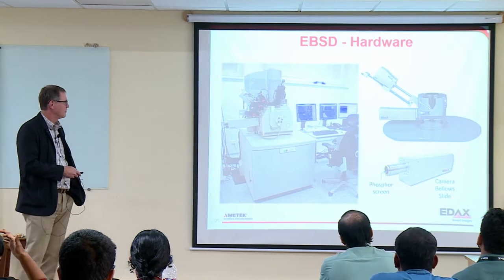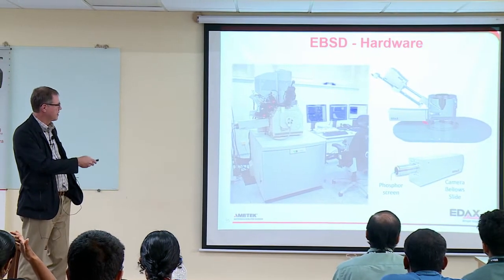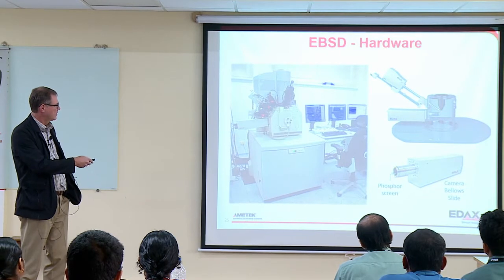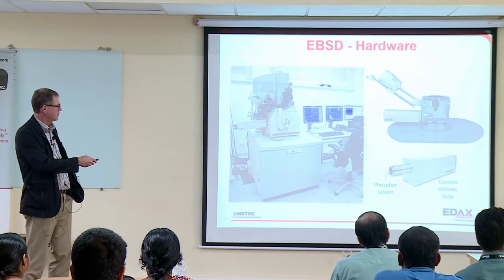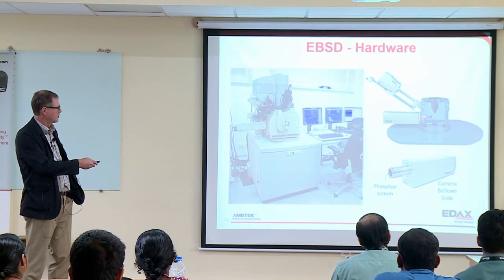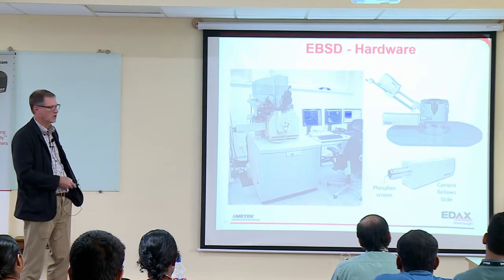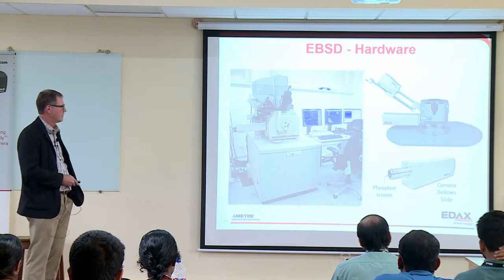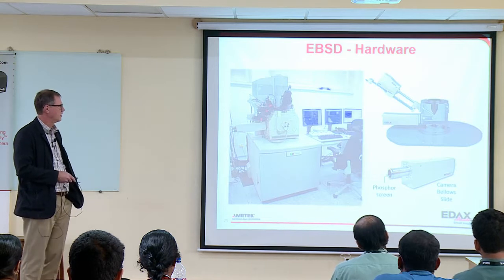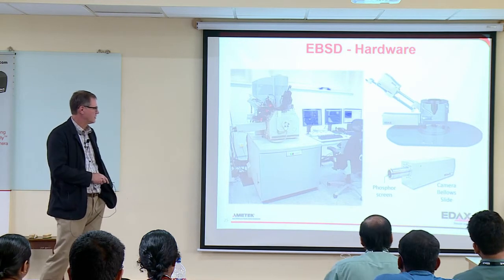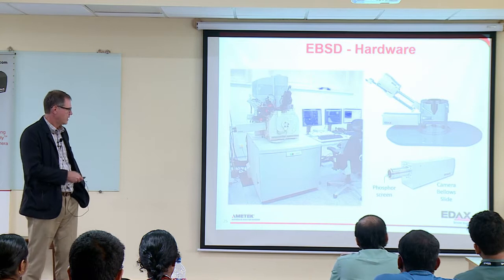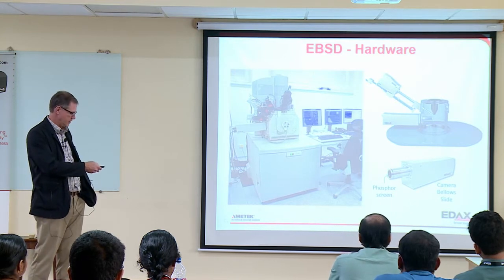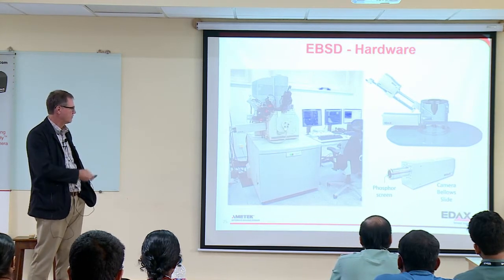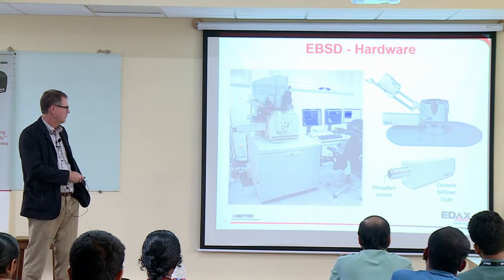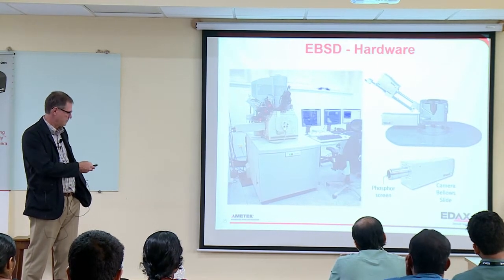So what's the hardware for EBSD? Once again, it's mounted here below the EDS detector. You can see the camera's inside this box, and there's a tube that goes in. The camera's actually inside the tube, so we can get it close to the phosphor where the illumination's happening, and we can get everything as tight as we can in the material. Inside this box, there's actually a bellows slide for vacuum integrity, and like I said, a phosphor screen.